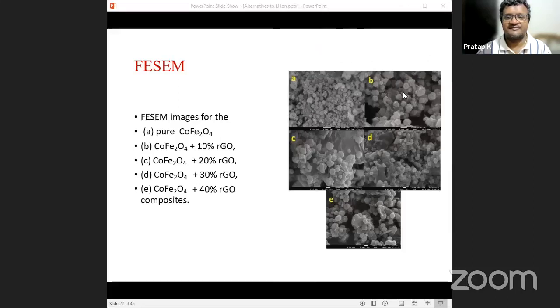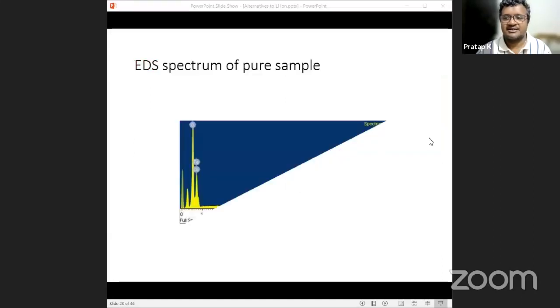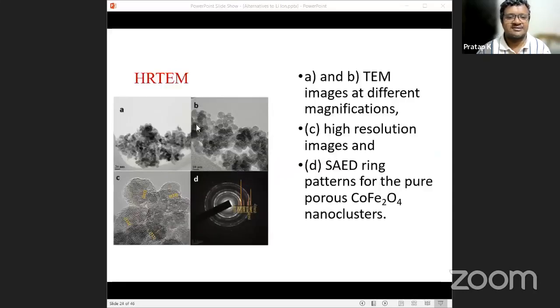Now, after that, we took the SEM, scanning electron microscopy images. So this one, if you look into the C figure, this is the RGO flakes, and nanocomposites are attached to it. So you could see clearly the FESEM images for all these different compositions of RGO. And this is the EDS spectrum. So it is clearly showing that cobalt, Fe, and oxygen are present in it. So this is the HRTEM, and in the HRTEM, you could clearly see that.